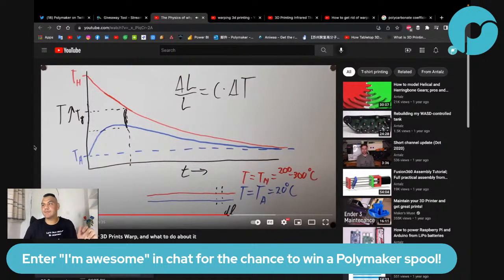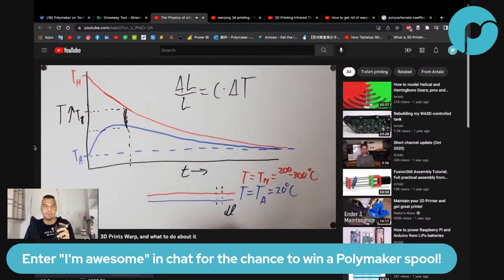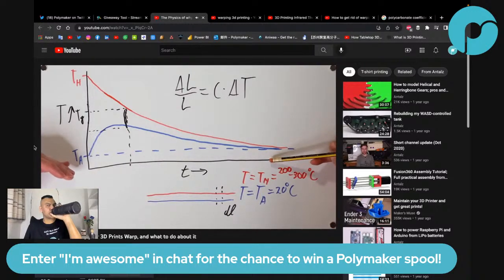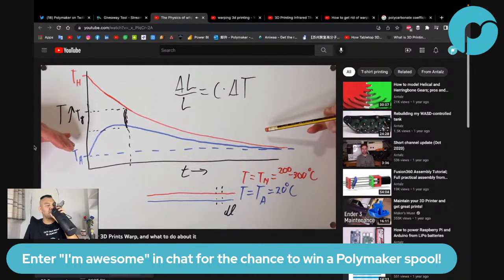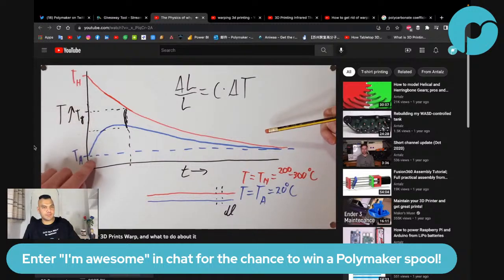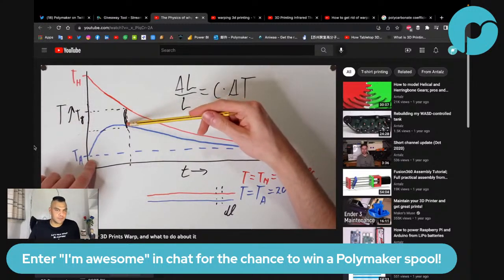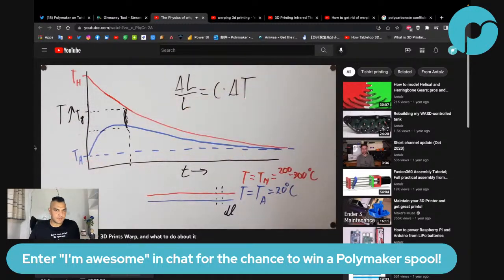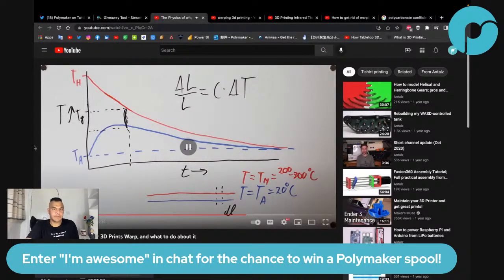The final thing you can do, which is the biggest thing, is to take this ambient temperature here and increase it, because that means that the lower layer has less of a gap to close, and then this difference becomes smaller automatically. And you also start losing a lot less heat to the atmosphere because it's warmer. And the way, of course, you do this is by putting your printer inside of an enclosure.